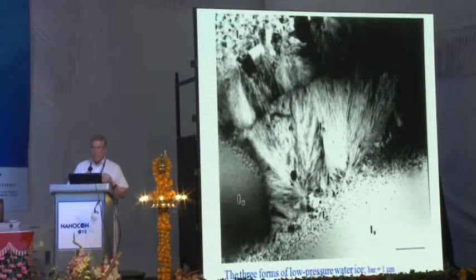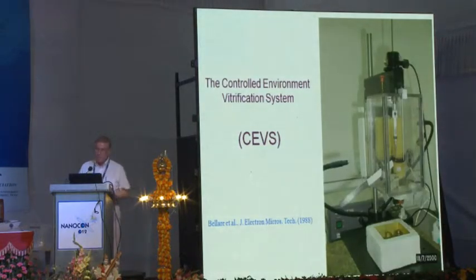the system. The problem is that in order to achieve this for water, and many of our systems are aqueous systems, you have to cool very fast, to the tune of 100,000 degrees per second, 10 to the 5th degrees per second. But this is feasible, and the way we do it I will explain. I will not bother you with the technical details. Those you can see in our many publications on the area.